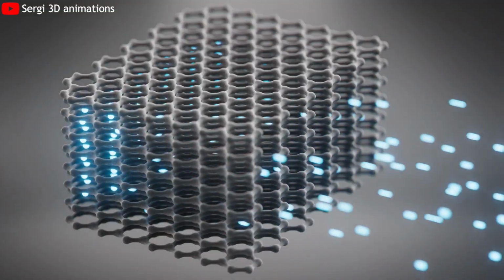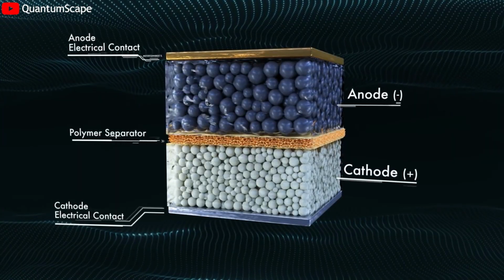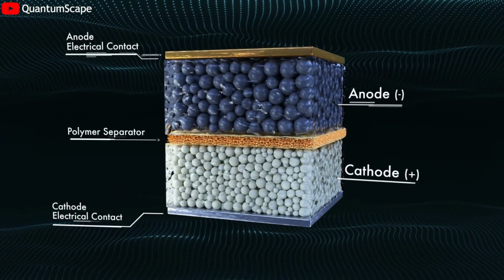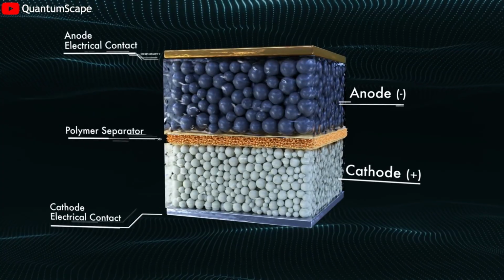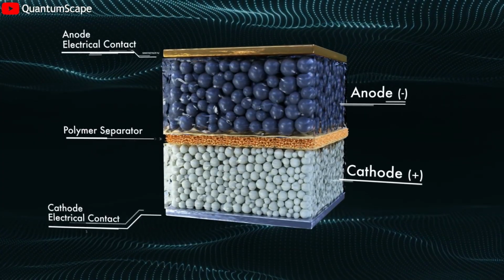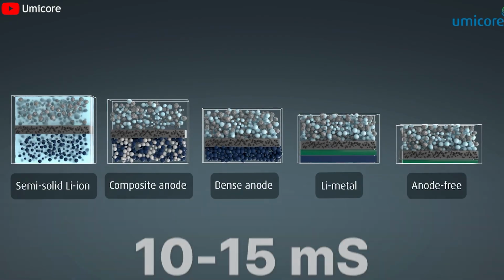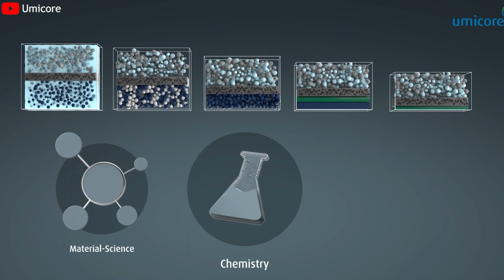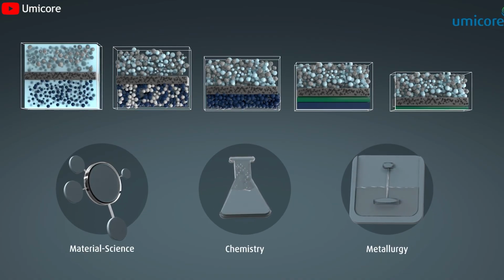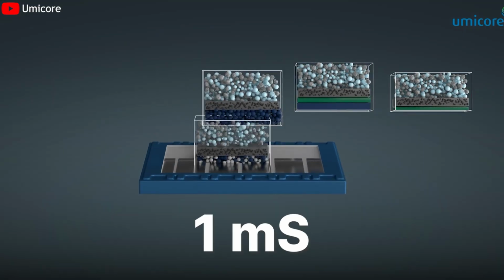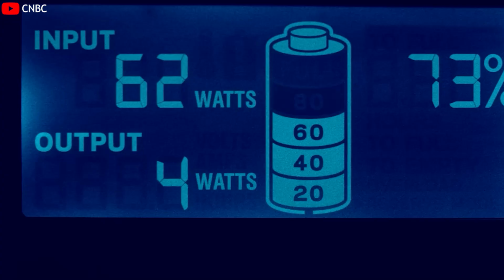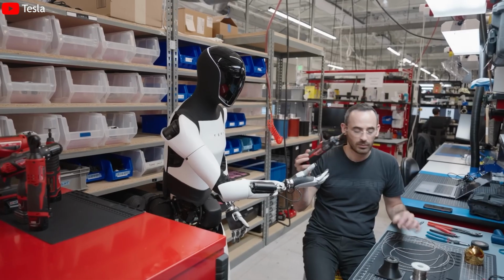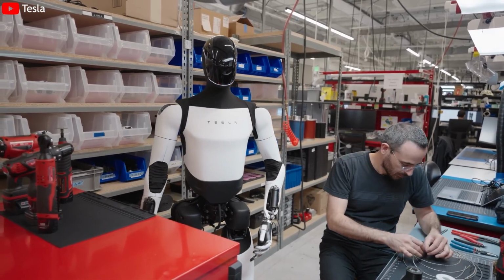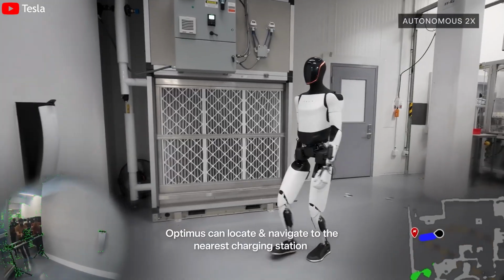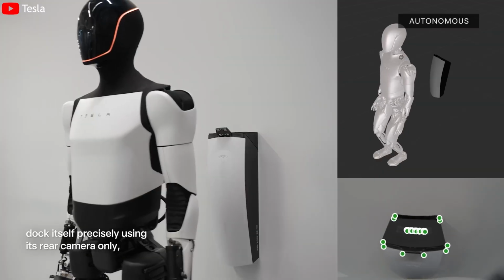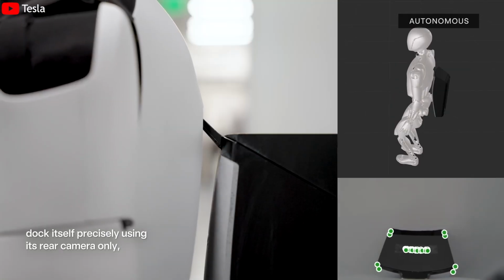This is precisely where solid-state chemistry fails. The interfacial resistance between solid electrodes and solid electrolytes is inherently high. Ionic transport across solid boundaries is slow, while liquid electrolytes routinely achieve 10 to 15 millisiemens per centimeter of ionic conductivity at room temperature. Many oxide-based solid electrolytes struggle to reach 1 millisiemens per centimeter. In practice, this means voltage sag. When Optimus demands torque, the solid-state battery cannot supply ions fast enough. Voltage drops below the inverter's cutoff threshold. The robot loses power mid-motion, potentially while holding a load.